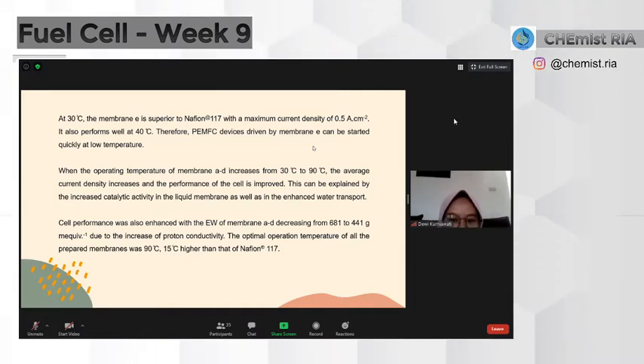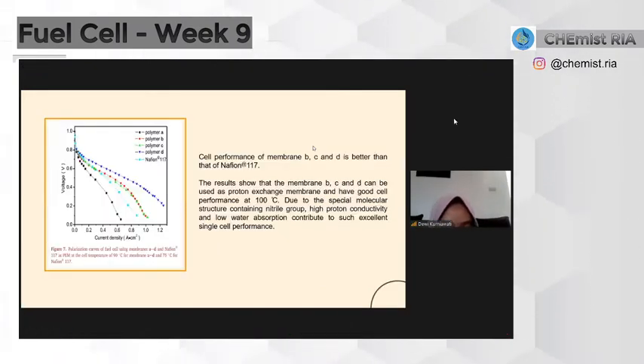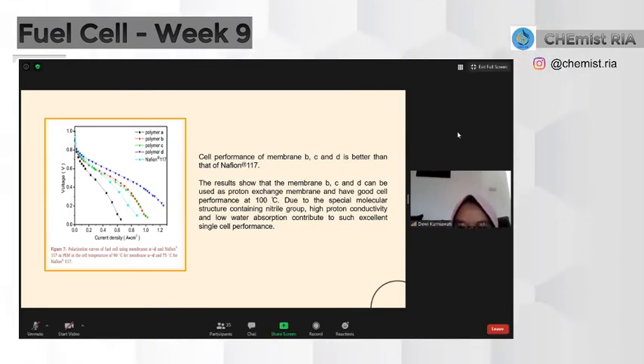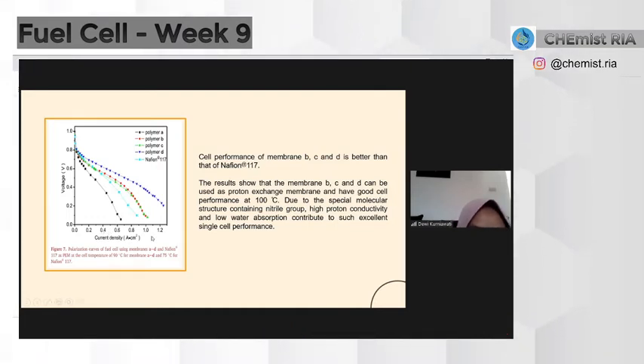Next, the cell performance of membranes B, C, and D is better than that of Nafion®117, and for comparison, see figure 7. The results show that membranes B, C, and D can be used as proton exchange membranes and have good cell performance at 100 degrees Celsius, due to the special molecular structure containing nitrile groups, high proton conductivity, and low water absorption, which contribute to such excellent single cell performance.